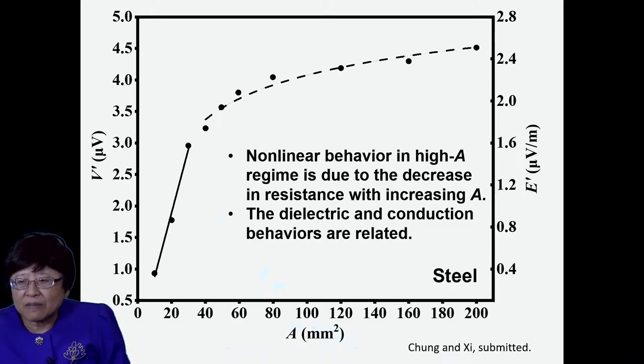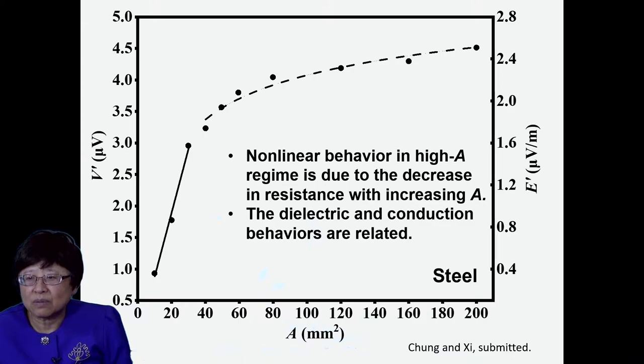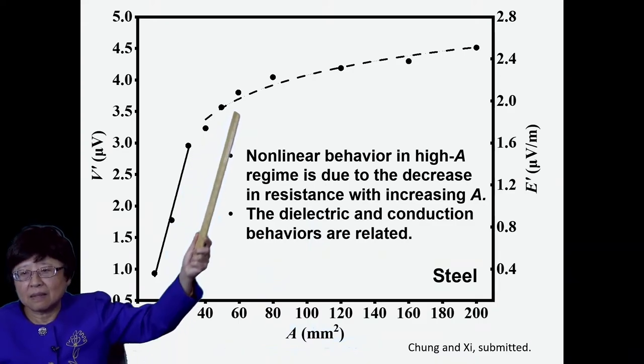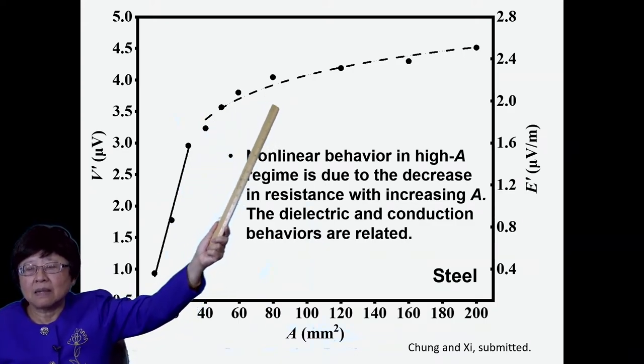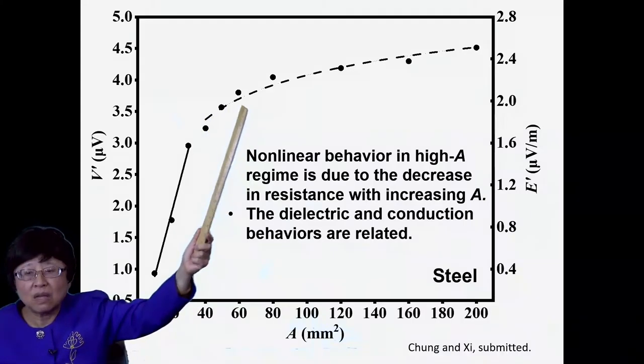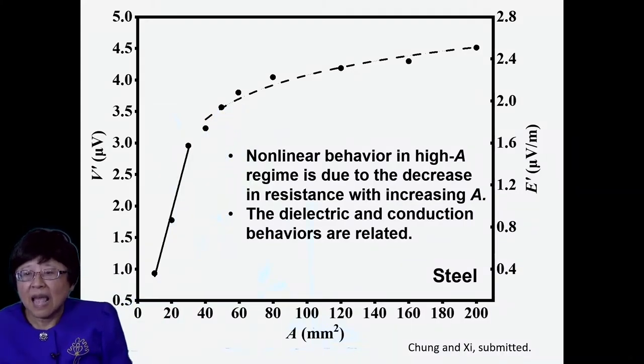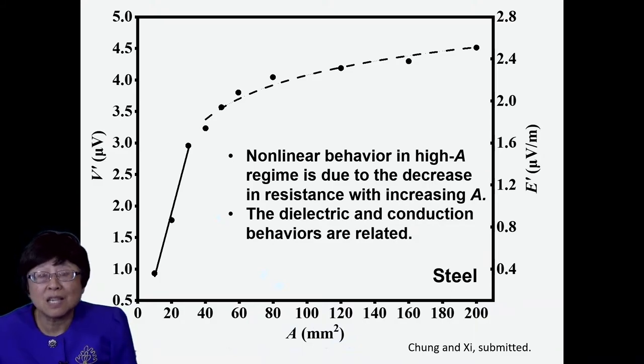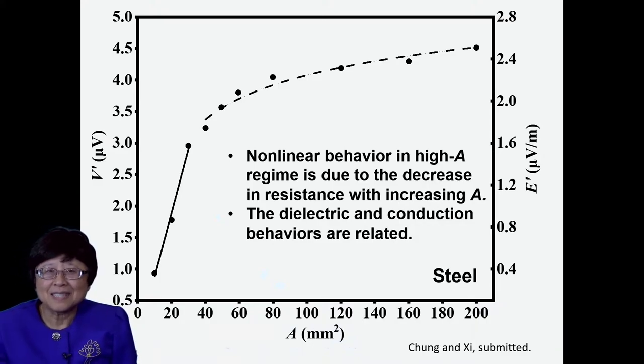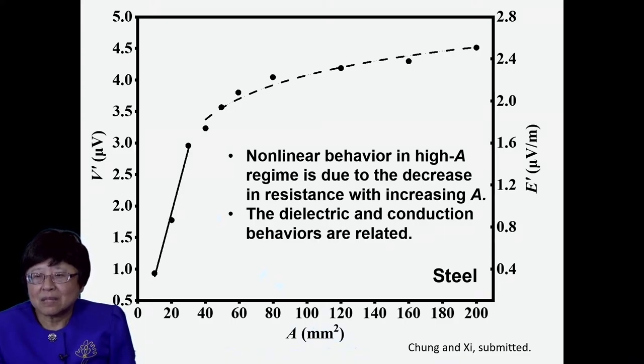And so the nonlinear behavior in the high area regime is due to the decrease in the resistance with increasing A. That's why the increase in the voltage slows down when A is large. It's because as you have more and more area, the resistance goes down, right? Resistance is inversely related to the area. And when the resistance is low, it's harder to support a high inherent voltage.